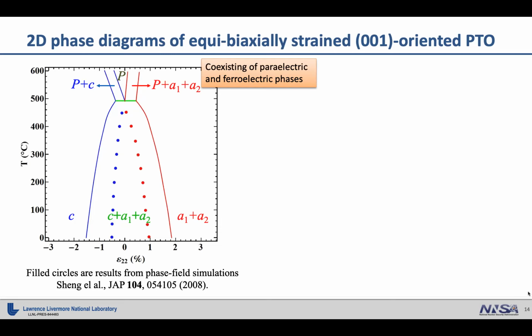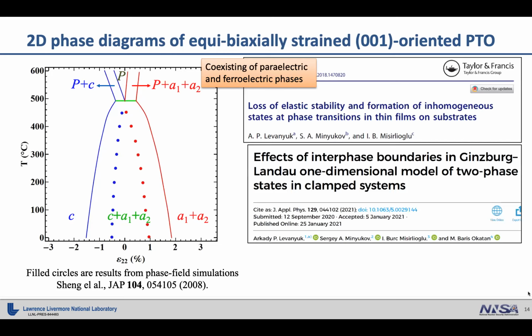other method. And we found in the literature that this finding is kind of controversial. And from these two papers, we have learned that, in short, when there are two phases coexisting at high temperature, it means it's a first-order phase transition, but the previous theory predicts it's second order because they assume it's a monodomain, and based on the monodomain Landau-type theory, they predict it to be second order. But if we release that assumption, it could be first order, so there will be coexistence of the paraelectric